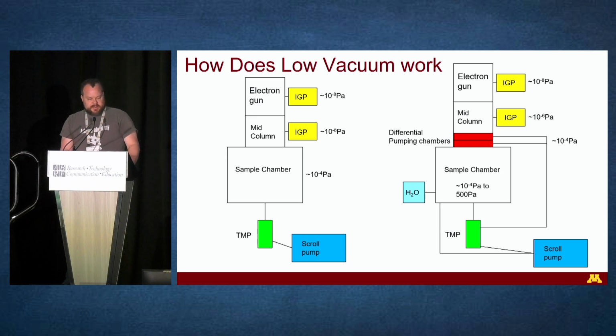So standard SEM on the left, you've got various pumps at the bottom, usually these days a scroll pump and a turbo pump to keep a nice clean chamber, no oil involved. Your samples would sit somewhere about 10 to the minus 4 Pascal range, and then your electron column is typically pumped to higher vacuum, 10 to the minus 6, 10 to the minus 8 for field emission guns at the very top end.